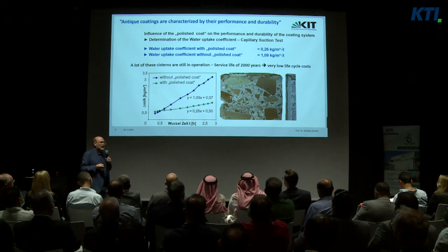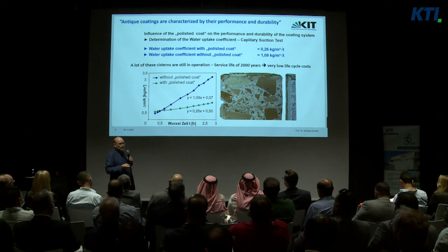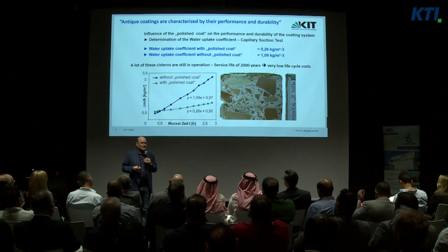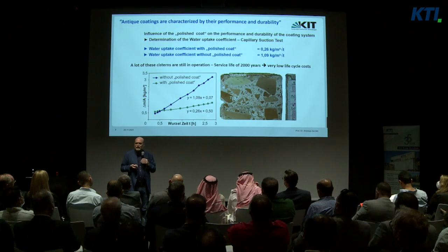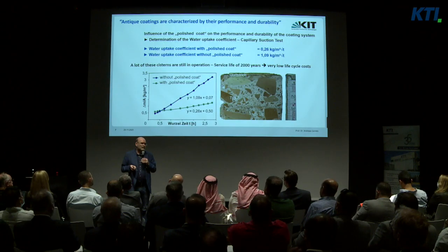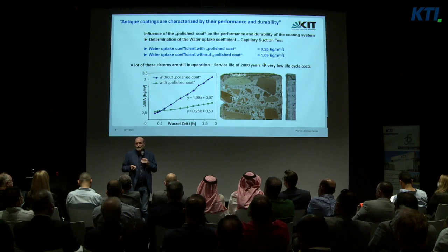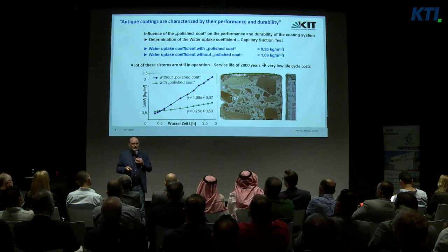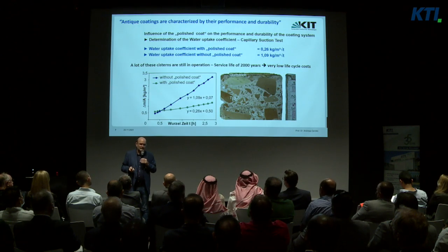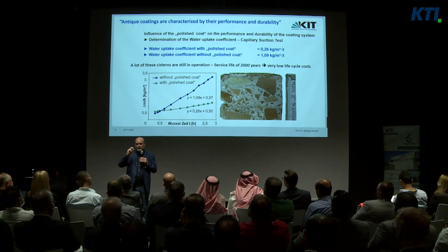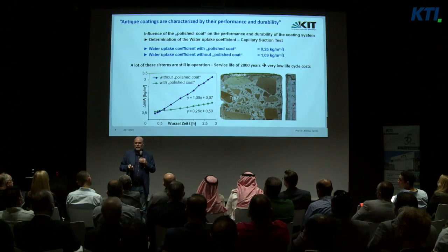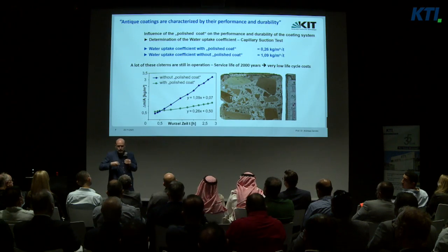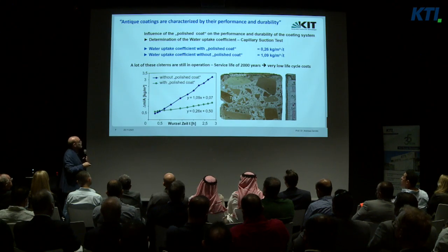So what we have done in cooperation with a small company, we developed this system with new raw materials, and now it's one of the best water reservoir coatings in Germany, because the durability is comparable with the durability of these systems. Only due to the opposite porosity profile. That's the reason for that. Very simple.